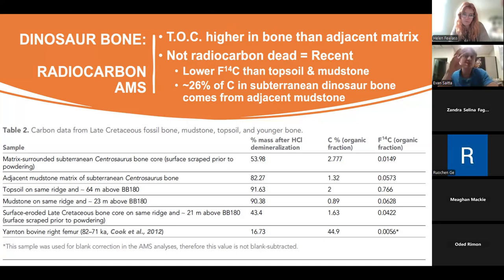Now, this is interesting. Based on this and using a simple one box model, we estimate that about 26% of the carbon in the subterranean dinosaur bone, while it's buried, comes from the adjacent mudstone. And what this means is that it's not just reflective of whatever is currently living in the surrounding mudstone. It's acting as a reservoir of sorts. There is some degree of residence within this bone. It might not be Mesozoic, mind you, but there's something going on and residing within this bone.